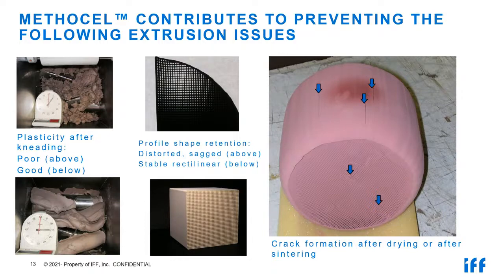So, for instance, typical reasons for crack formation are wrong batch processing, wrong mixing, uneven distribution of water in the batch. It has to do with simple things like cutting the profile after the extrusion step, with handling the profile into the drying room, with the drying room conditions, with the air distribution in the drying rooms, with calcination conditions, and so on and so on. There are many, many contributing parts, but cellulose ether, in some cases at least, is able to solve some issues which you cannot solve with any other tools. Next slide, please.